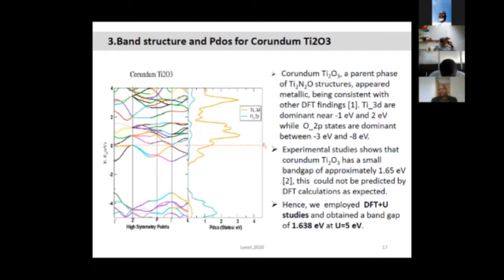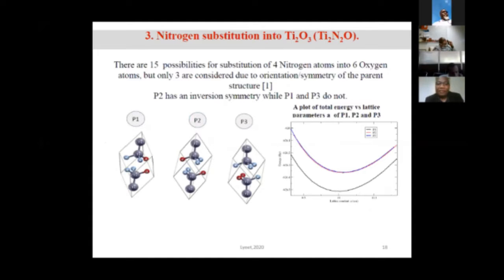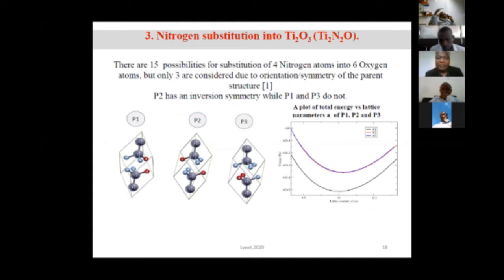Okay, fine. So I was saying that since this material appeared metallic, yet it's expected to be a semiconductor, we employed DFT plus U, a corrective approach used to relieve DFT of its electronic band gap approximation. It is reliable and has been used before. It has a critical advantage of considerably low computational cost. Of course, we have to optimize the U before we use it, so we tune different values of U while seeking agreement with the experimental data of the system's properties. DFT plus U corrects the localization of d and f electrons in highly correlated systems, and here it was applied to titanium 3d. We corrected our band gap to 1.638 when U was equivalent to 5 eV.